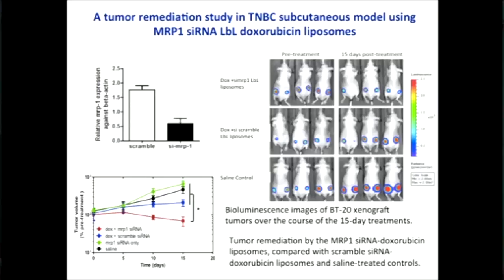All right, so this gives you an example of the results that we see. And maybe it's easier just to start on the right-hand side. We're looking at these mice that have tumors implanted pre-treatment. And then we give them a treatment, and after 15 days, we measure how much the tumors increased or shrank in size. And as you can see, when we have doxorubicin combined with the siRNA, we see significant tumor shrinkage, and in some of the mice, the tumors go away altogether.